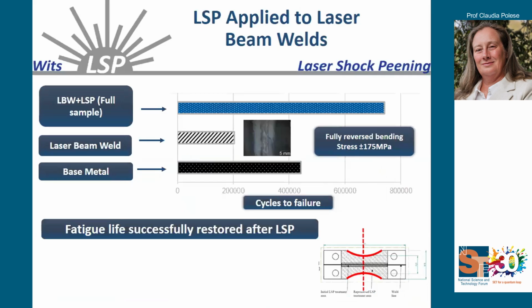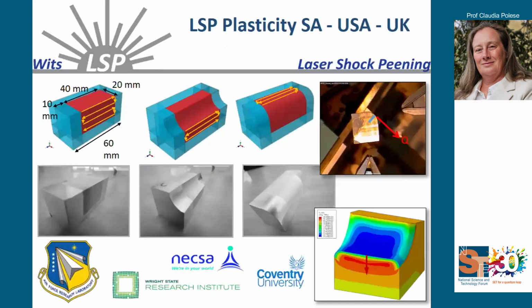In terms of mechanical performance, what we saw is that by integrating laser shock peening as a post-processing technology, we are not only drastically increasing the performance of the weld, but actually going beyond the performance of the base material. It basically means that we are almost doubling the performance, as if the joint was not even there. So the process has big promise.